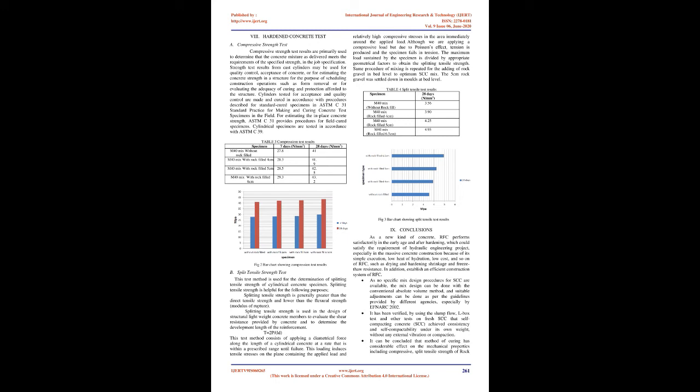7. Mix design. The mix design of self-compacting concrete is a trial and error method. Many references are available for mix proportioning of SCC. Here we use mix proportioning based on previous investigation strength data using the Japanese method and also based on the EFNARC 2002 guidelines. In the Japanese method, coarse and fine aggregate contents are initially fixed so that self-compactability is achieved by adjusting the water/powder ratio and superplasticizer dosage. Strength requirements are assessed from field trials of SCC at a later stage.